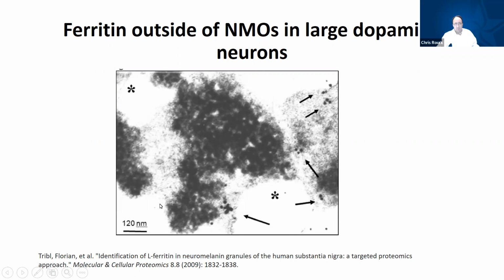In this electron microscope photograph, you can see small black dots that appear to be layers around this neuromelanin organelle. It's not possible to determine if those dots are ferritin except through the use of something like immunogold markers. These immunogold markers are tagged with anti-ferritin, so they're attracted to ferritin, and you can see at least some small number of them found their way into this structure. Obviously, there's not a one-to-one match. There'd be an enormous number of immunogold markers, but this was an indication that there is ferritin outside of these neuromelanin